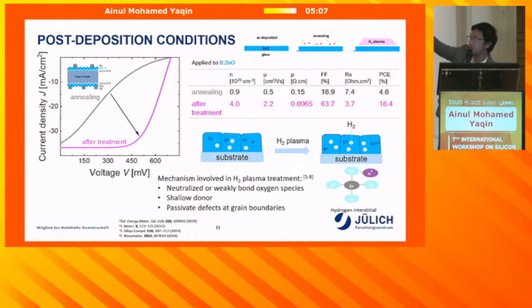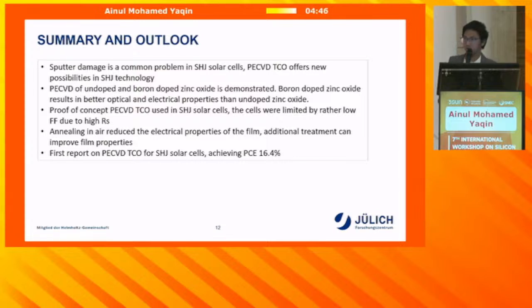In this case, the resistivity of our film goes down again, which you can see in the solar cell results. We have a huge improvement in the fill factor and also a drop in the series resistance, which results in an efficiency of our solar cell of around 16.4%. So I think that's pretty much the talk about our PECVD TCO. Basically, we have the sputter damage, and we can utilize PECVD as a new route to develop the TCO layers, especially in heterojunction solar cells. This is our first report to utilize this in solar cells, showing an efficiency of around 16.4%.